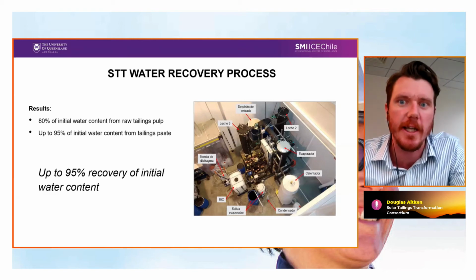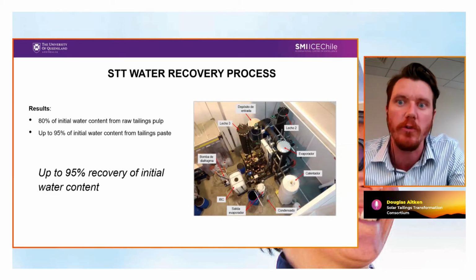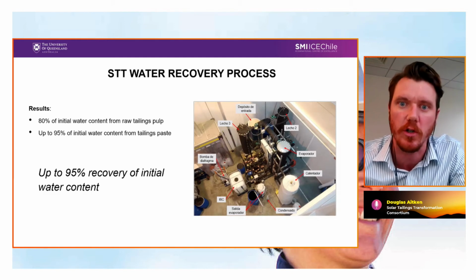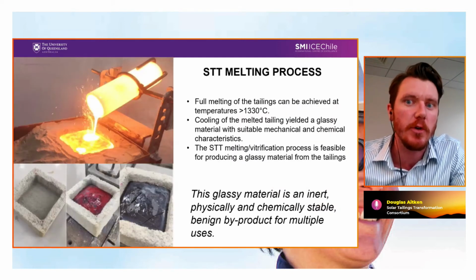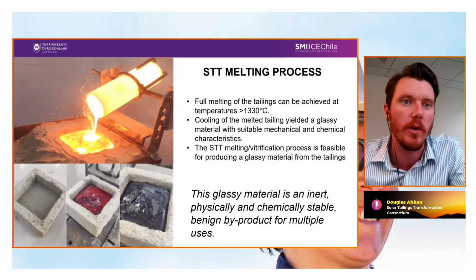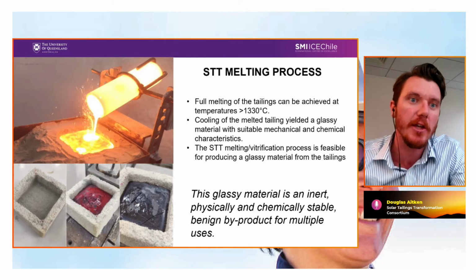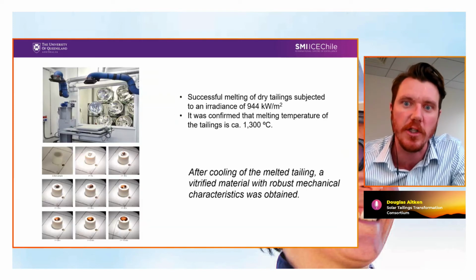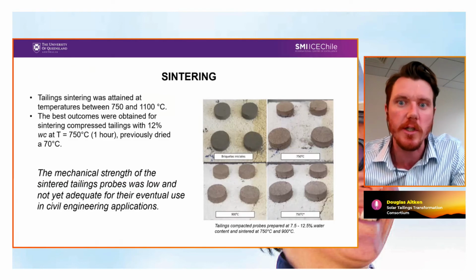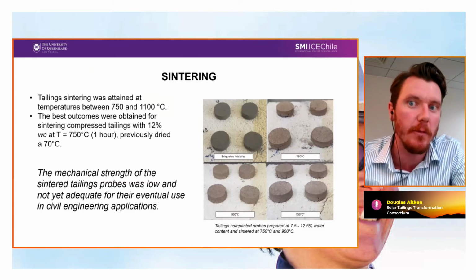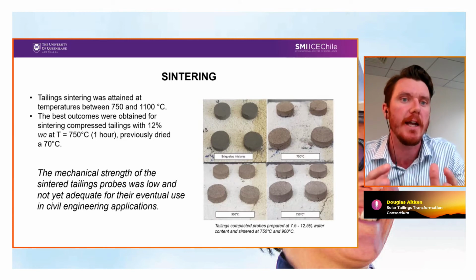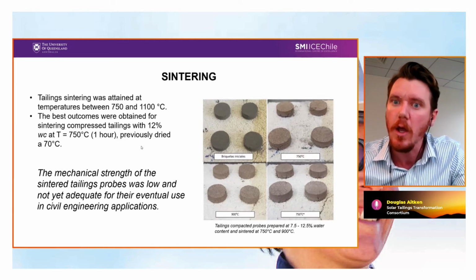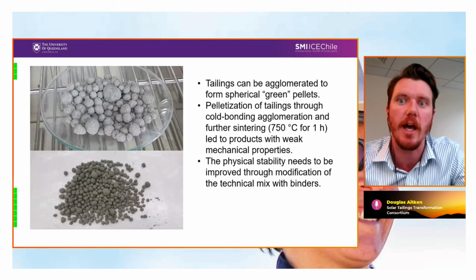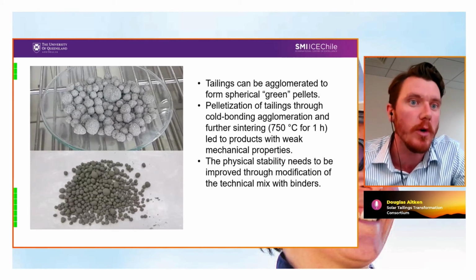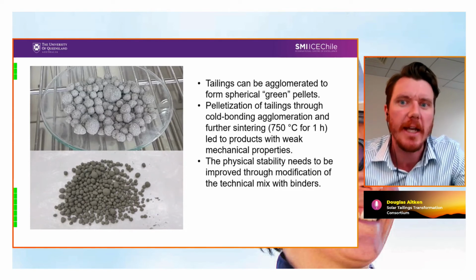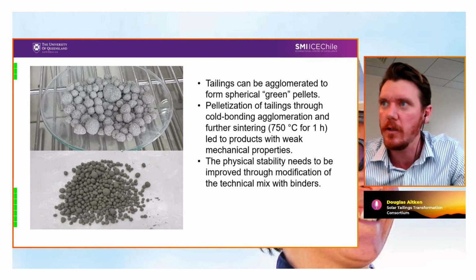Using the evaporator condenser column system, we recovered 95% of the initial water content. We were able to melt the tailings and produce stable glassy materials at around 1,330 degrees using a conventional oven, and then also with the concentrated solar simulator. We produced sintered briquettes from the dried materials, although we found the mechanical strength of these briquettes to be quite low. But we also produced agglomerated pellets using a cold bonding technique, and we were able to sinter them at high temperatures, but again, the mechanical properties were found to be quite weak.